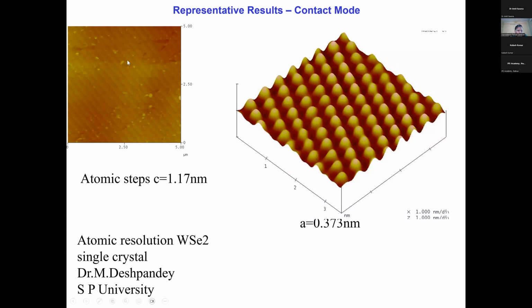By drawing one line, you can see steps in the height, from one step to another step, it is around 1.17 nanometer, which means about 11.7 angstrom. One nanometer is 10 angstrom. So this is equivalent to the unit cell dimension of the WSe2. How is the growth happening? A crystal normally grows due to some defects, etc.